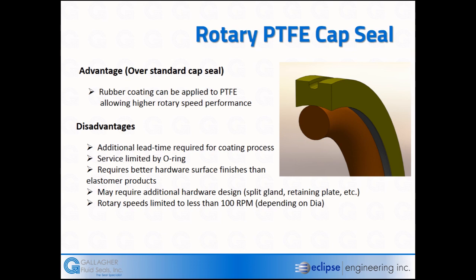So we have a process where we treat the PTFE and put a chemical on the back side of it. And when the rubber and the Teflon element are put together in these rotary joints, it causes a mechanical bond to occur between the rubber element and the coating that's applied to the back side of the Teflon, which causes the friction to be increased dramatically between those two elements, so that we can drive all of the rotary action at the dynamic surface.